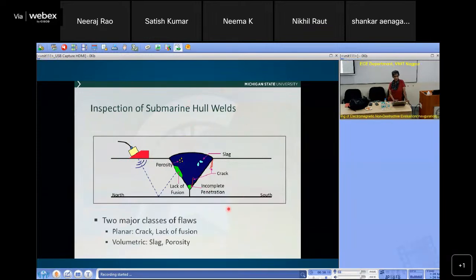And in this case, basically the signals were all generated by the Navy, and all we did was interpret those signals. They wanted to know: is it a crack, or is it just a lack of fusion between the weld material and the steel, or there can be porosity, air bubbles, or slag, some kind of impurity in the weld material. So they were only interested in finding out these different classes of defects, not even to image it.